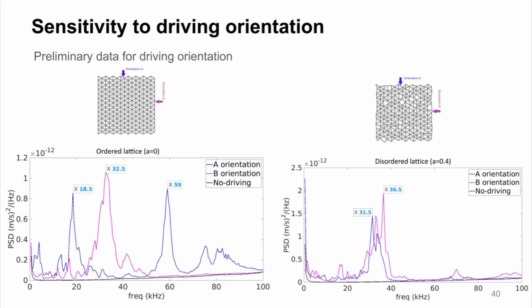I also tested the sensitivity to driving orientation with respect to the lattice. Two of the orientations I tried are shown in the metamaterial picture here. The first orientation, orientation A, is along one of the axes, whereas the second, orientation B, is at an angle to the axis of the lattice. I see that for ordered point distribution, the orientation does change the frequency response, the power spectral density of the metamaterials, whereas for intermediate disordered metamaterials of 0.4, I find that there does exist isotropy in the characteristic power spectral density curve.